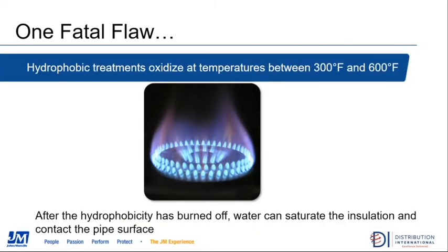The one thing you have to be extremely cautious of and keep in the back of your mind when you're designing your insulation systems and selecting the materials is that most of these insulation products get their hydrophobic or water repellent properties by the addition of some type of a chemical treatment, usually some type of a silicone or an organic treatment. And most of those treatments oxidize away at temperatures between 300 and 600 degrees Fahrenheit. So if the insulation material sees those elevated temperatures for a long enough period of time, the hydrophobic or water repellent properties will oxidize away, and that will no longer be a feature that the material can offer.